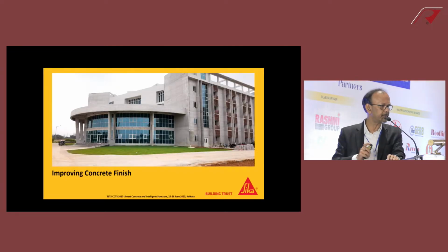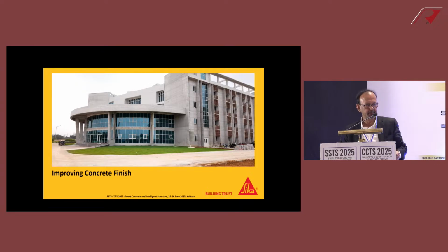One more important thing, and this is an IIT building in Tirupati. Why I mention it is, we are all talking about finish of concrete, which is also important, because getting the concrete good is all. It has to be placed within the formwork so that when you release the formwork, it looks very good, so that you don't have any blemish, any bug holes or any porosity, because corrosion, carbonation attack, we know, will bring down the pH level of concrete from 13.5 or 13 to 9.5, where the first stages of corrosion you will notice as reddish or brownish spots.